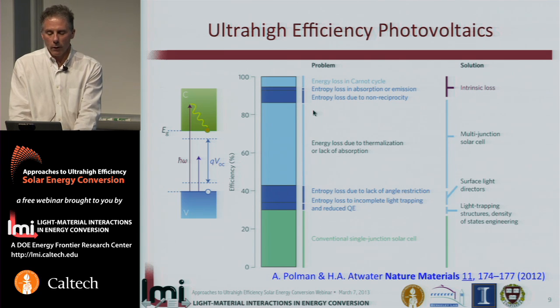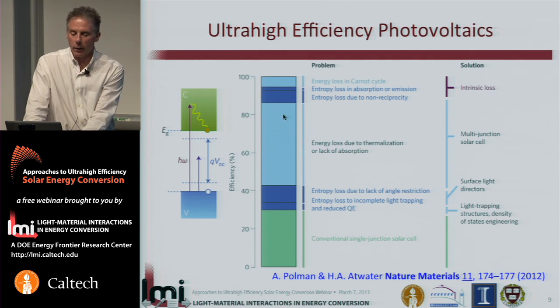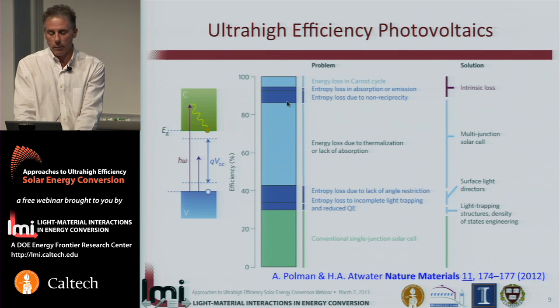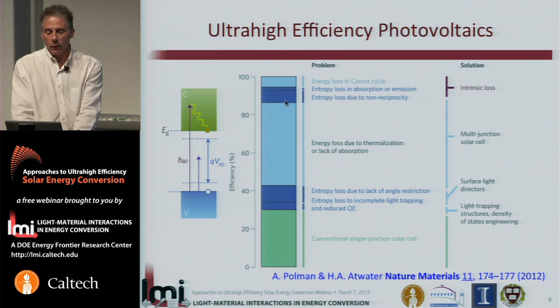There are some other features up here that separate current record and real-world efficiencies from the absolute limits of photovoltaic efficiency that have to do with some more exotic approaches. For example, the fact that typical PV materials and media obey time reversal symmetry, and therefore they transmit photons in both directions with the same transmittance. If we could make truly one-way materials, and in fact there are some emerging ideas in the metamaterials and nanophotonics arena to make materials that disrupt this time reversal symmetry, then one might possibly recoup an additional efficiency element.